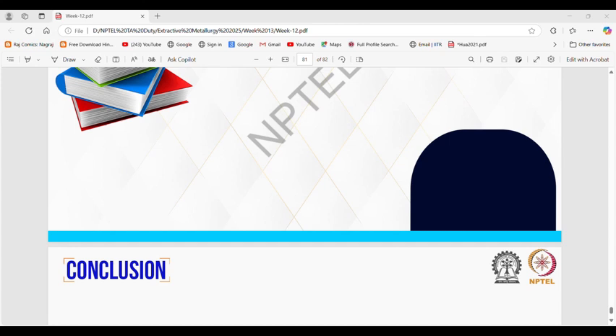Then commercial metal production using hydrogen. So they are producing tungsten. The raw material is WO3, and the method or equipment they are using is solid state reduction in a rotary kiln. And they are producing pure tungsten grade powder, which can be used for further applications. Then they are producing molybdenum metal powder with the help of MoO3 hydrogen reduction processes in the form of solid state reduction in various furnaces such as Pusher furnace, rotary kiln, walking beam furnace, and fluidized bed reactor.